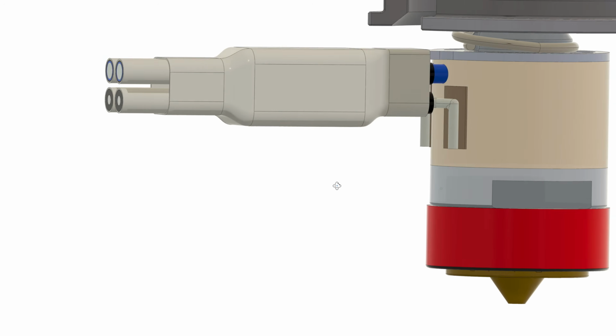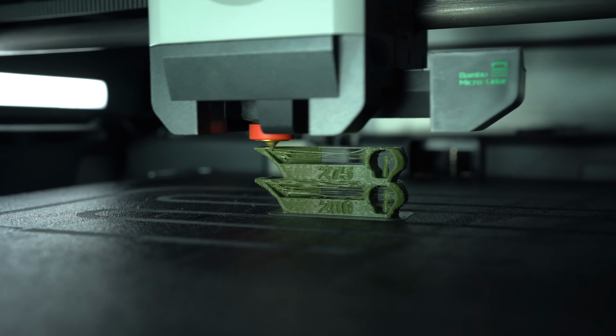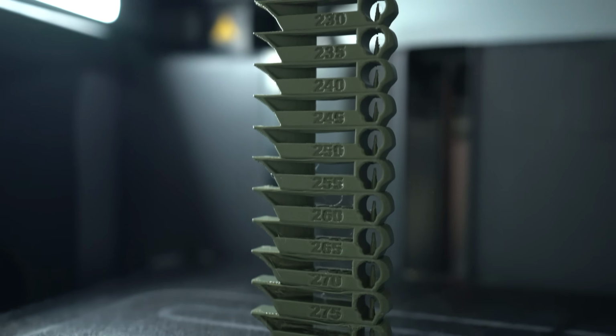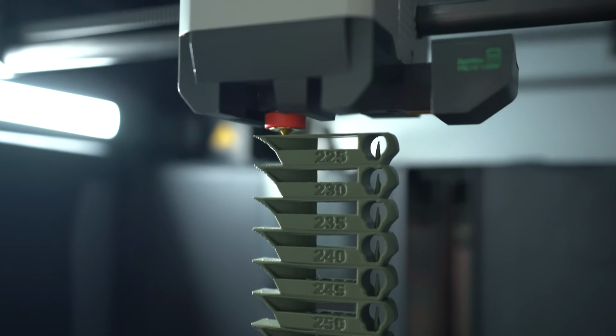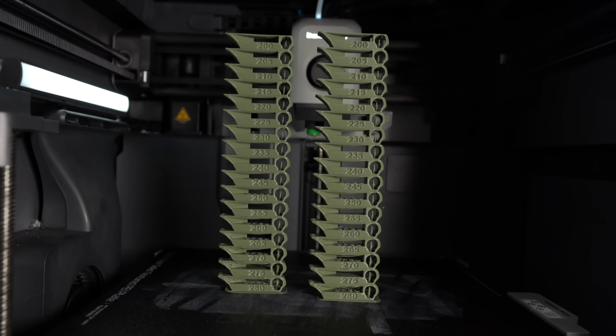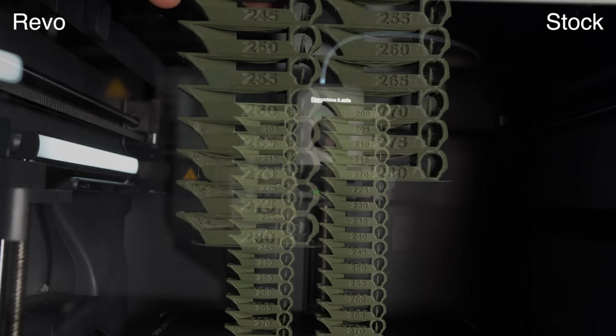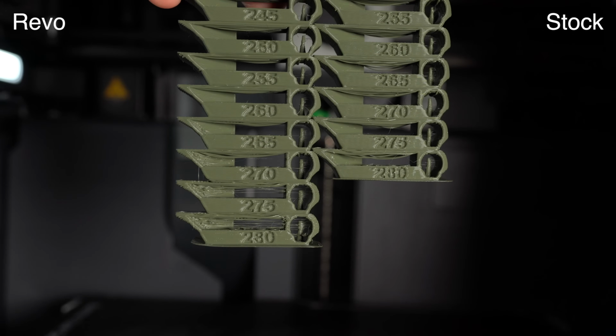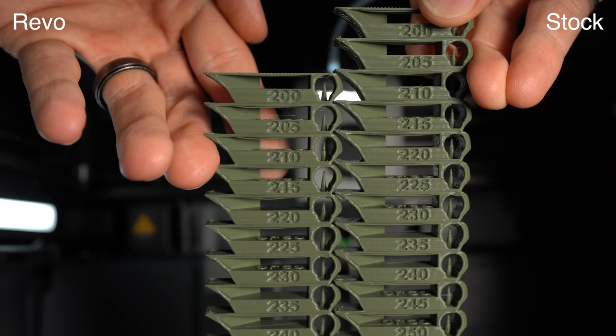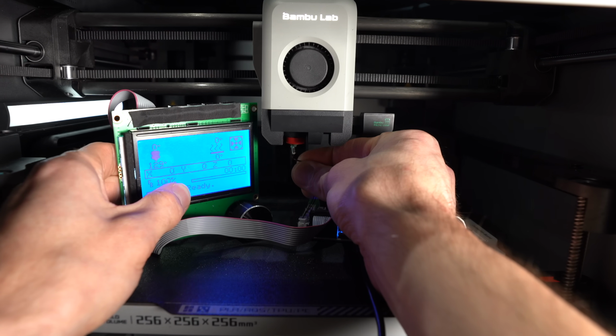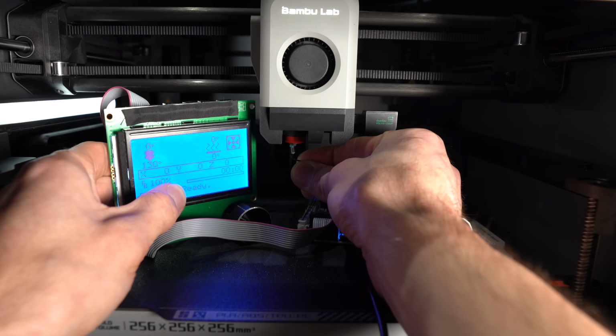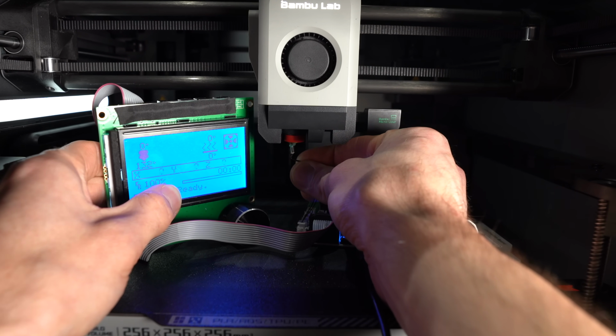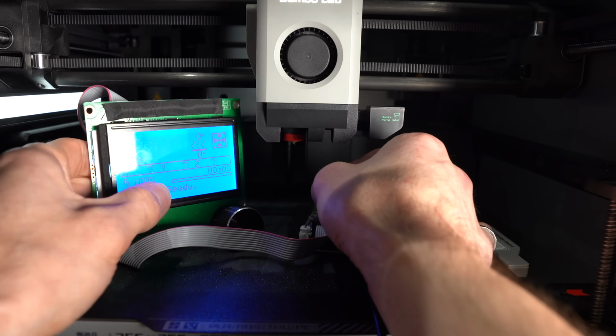In order to calibrate, I printed a temperature tower on each. When comparing the results, I found that the Revo prints approximately 10 degrees hotter. 280 on the Revo is really like 290, and 200 is like 210. When I line up the towers with the 10 degree offset, the adjacent tiers look similar. I was able to confirm this finding by measuring the tip of each nozzle with an external thermistor. The Revo measured approximately 10 degrees higher. We can't do anything in firmware to correct for this, so we'll just have to adjust our filament profiles accordingly.